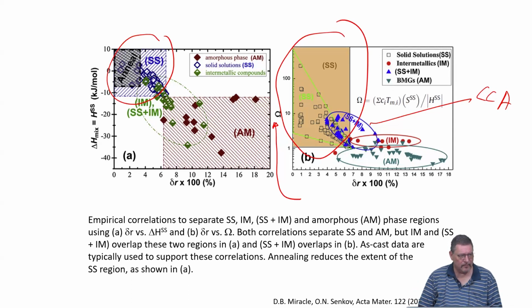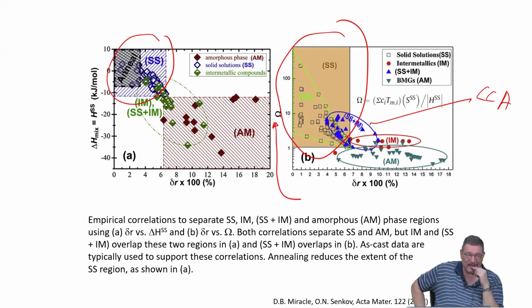Yes. That will give all phases. That will give, no, as I said, you have to put in the possible stoichiometric phases. After that analyzing from the experimental data, we can give that. Yes, or if you have some literature or you do yourself density functional theory calculations, because there you can just look at the energetics of different configurations like AB, A2B, A3B2 or so. This can be done on a fairly simple ensemble, let's say 50 atoms or so. And there you can easily converge into finding structures and their relative energies with respect to maybe a solid solution, for example.